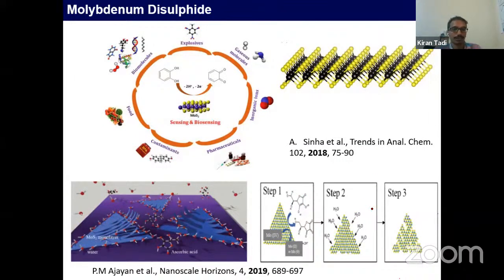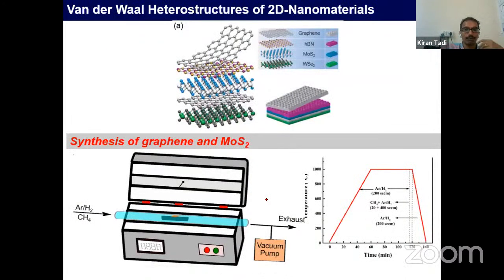It is converting, so we thought why not use this molybdenum sulfide with graphene and make a van der Waals heterostructure, so we can prepare a stable electrochemical sensor which is highly sensitive as well as stable. That's why we prepared a van der Waals heterostructure having molybdenum sulfide and graphene one upon each other, interacting through a van der Waals interaction.